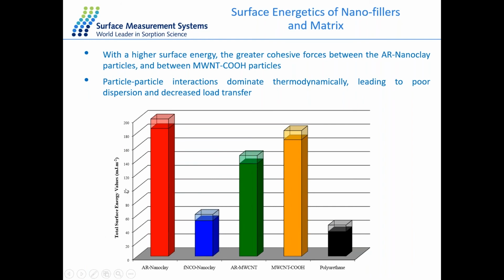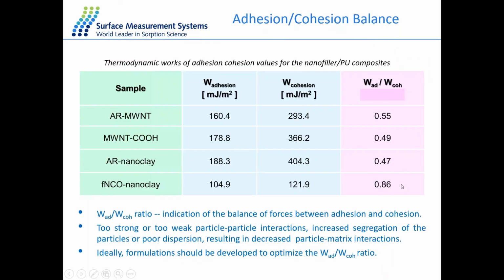So this is looking at the total surface energy of each of our components. And what we can see is that we have a higher total surface energy for our as-received nanoclay and our carbon nanotubes with carboxylic acid groups. So this can give an indication of these two samples having a higher particle-particle interaction. And this is quite important because once we start to blend into the polyurethane matrix, it can give an indication of these two materials having a much poorer dispersion into the polyurethane matrix due to this higher total surface energy contribution. We've also calculated the work of adhesion and cohesion and calculated the adhesion-cohesion ratio.